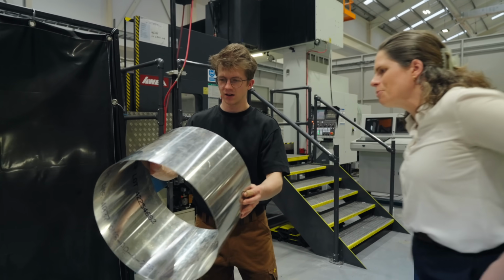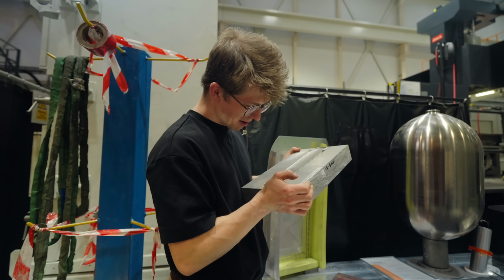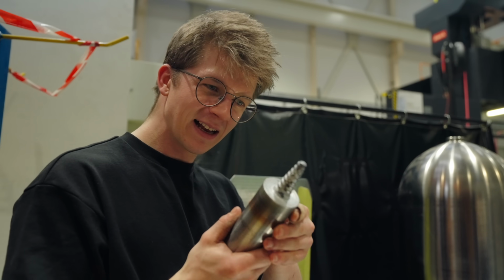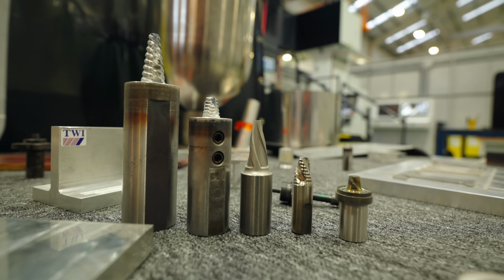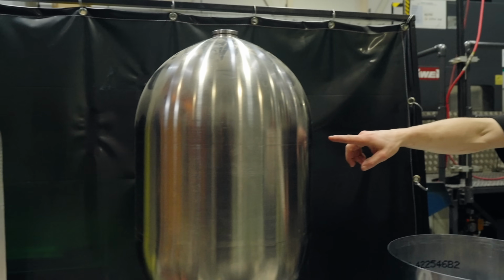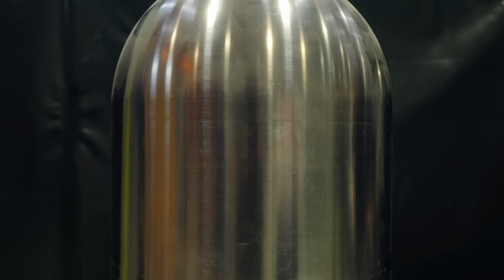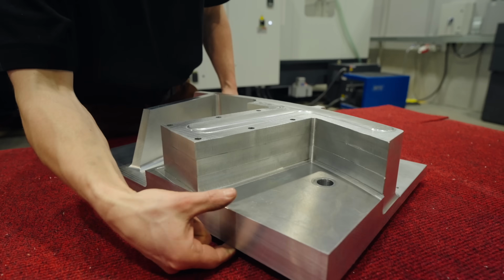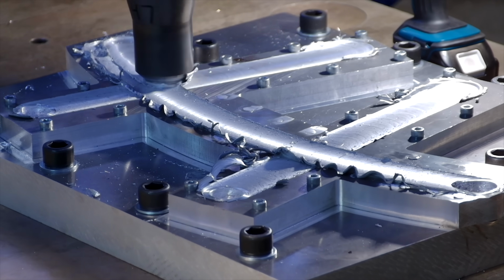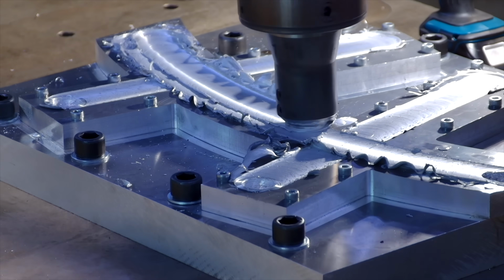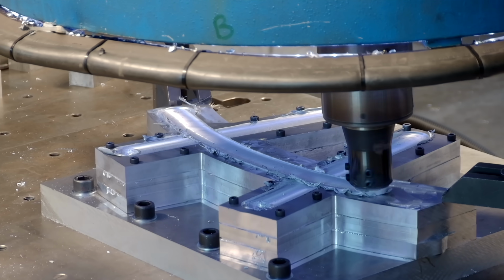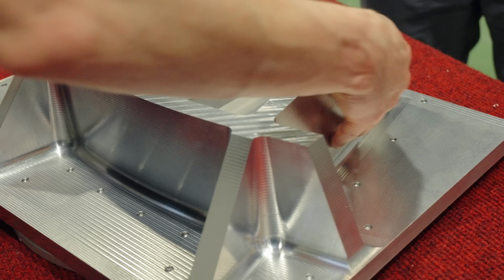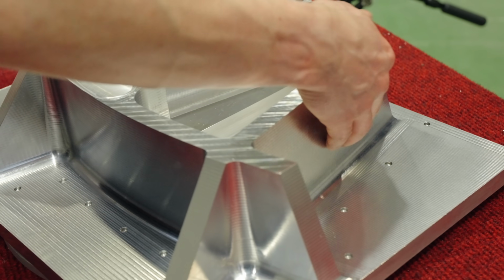From 0.8mm thick all the way to 150mm thick. If you've got a big enough machine, you can friction stir weld it. Dissimilar metals too. Gets used on pressure vessels. This one's made out of titanium, to even producing near net shaped components where, by stacking up plates cut close to size and friction stir welding through that stack, you can create your final component in the friction stir welded material. I've been absolutely blown away by my visit to TWI.